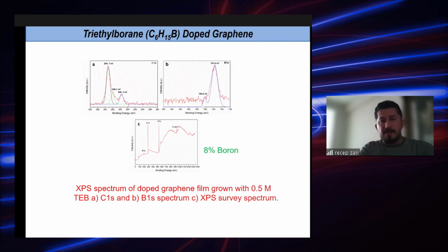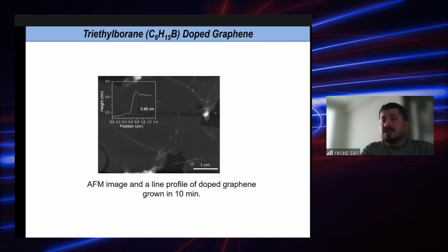The TEB one. So again, we check the thickness of the film here, and we try to see whether it is one layer or two layers. As you see, the thickness is around 0.8 nanometer, and this is called single layer in the literature. Yes, I know it's a bit thicker than the pristine one, but it is expected, and it is concluded as a single layer, and we can discuss it if you have any question.